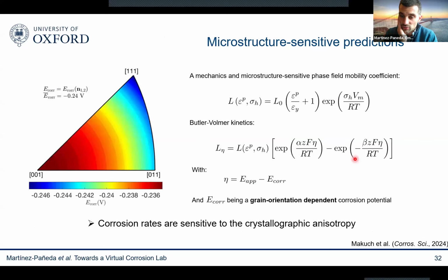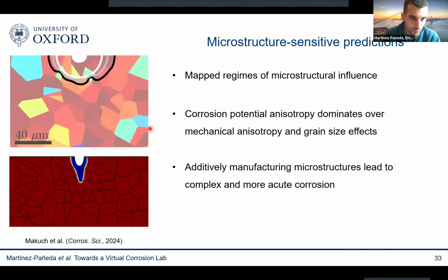Another important effect is the susceptibility to microstructure. So we know that corrosion rates are sensitive to crystallographic anisotropy. So we can enrich the definition again of this mobility coefficient. We can solve an electrochemomechanical problem with Butler-Volmer kinetics, and we can define a grain orientation dependent corrosion potential. And when we do that, many possibilities open here. Of course, you can combine this, for example, with EBSD images that you take from your lab, with all your favorite crystal plasticity model, and you can learn a lot about what role does microstructure play, because we're interested not only in the mechanical anisotropy, but also in the corrosion anisotropy.